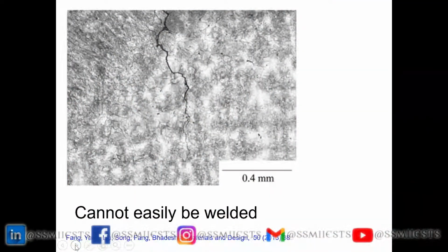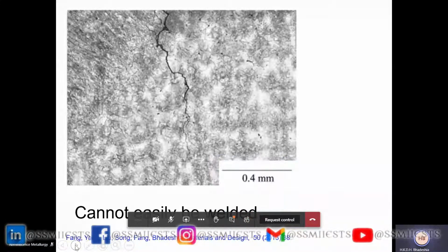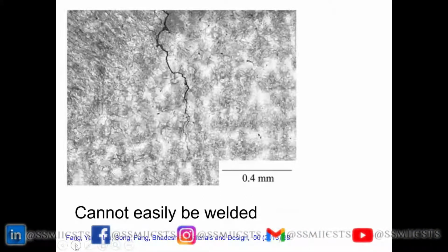and it's a very major problem, that you cannot weld it, right? Because it contains about 1 weight % carbon. So whenever you weld it, you will spontaneously get cracking. Okay. So how do we solve this problem? We want an extremely strong steel, which at the same time has a reasonable carbon concentration, and yet we should be able to manufacture it in very large quantities.